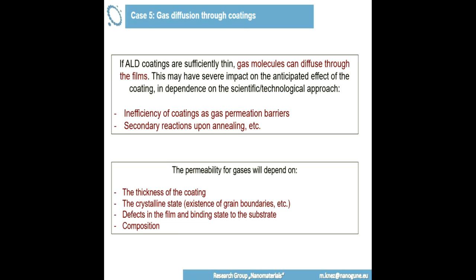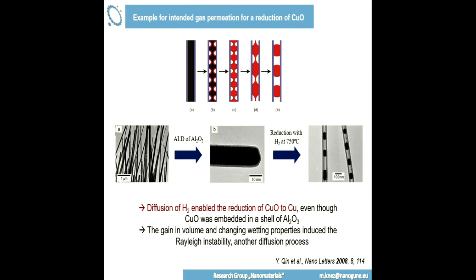If they are too thin, or if they are crystalline, if they have too many grain boundaries, they will allow gas permeation. And here is an example from a scientific perspective. This is a copper oxide nanowire coated with aluminum oxide. This is just a very thin film, I think 5 nanometers or something like that. And then, if you expose it to hydrogen gas at elevated temperatures, the gas can permeate through the coating, and it can reduce this copper oxide to copper.